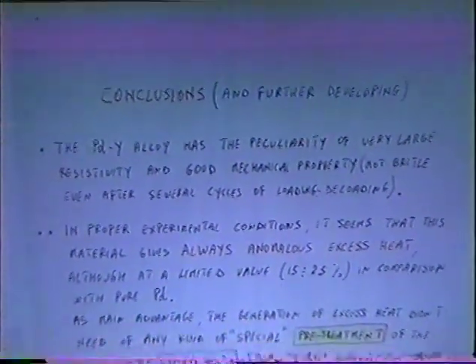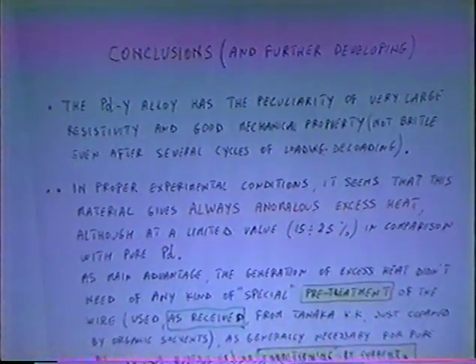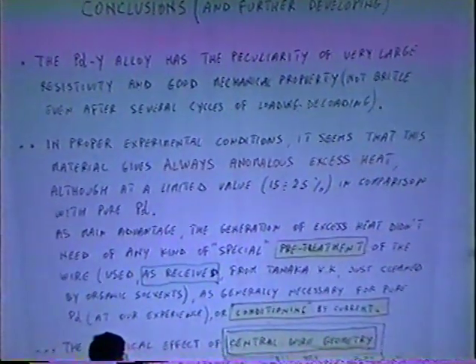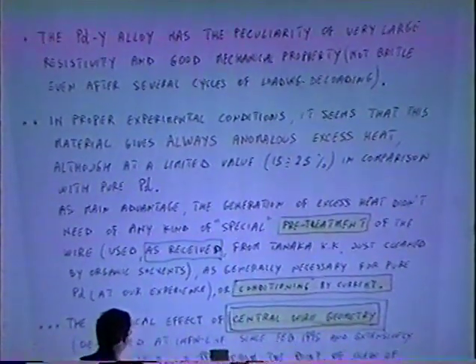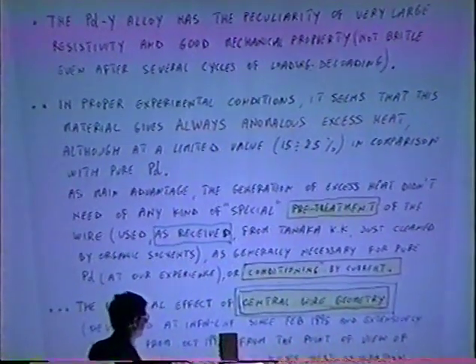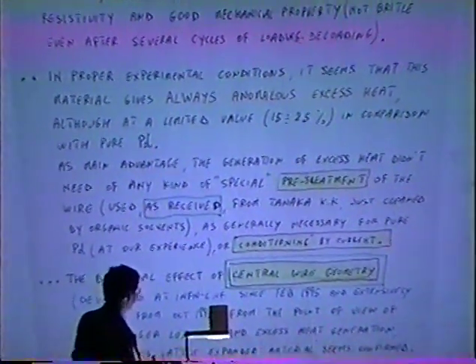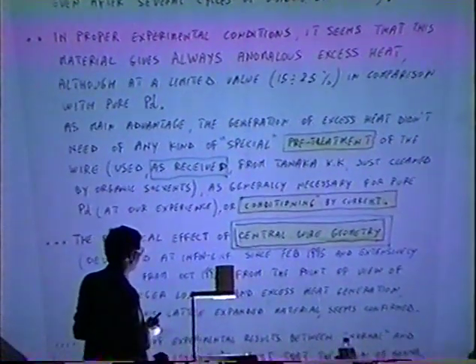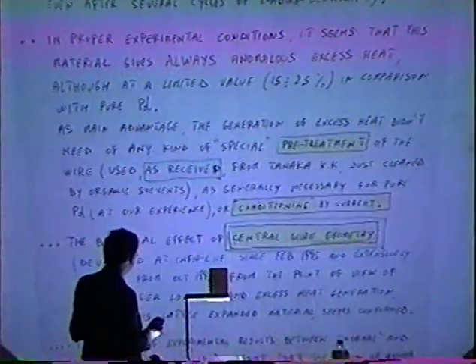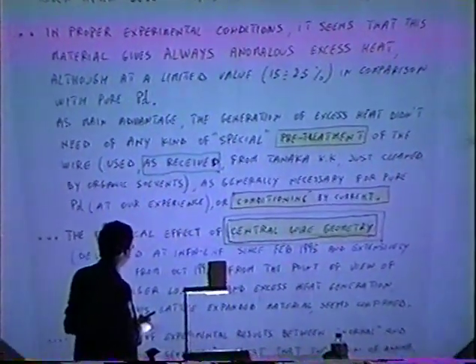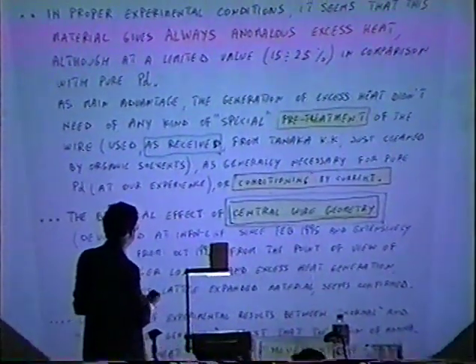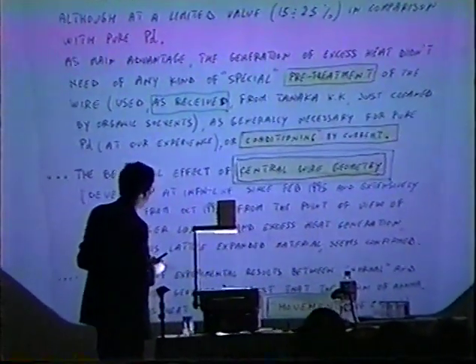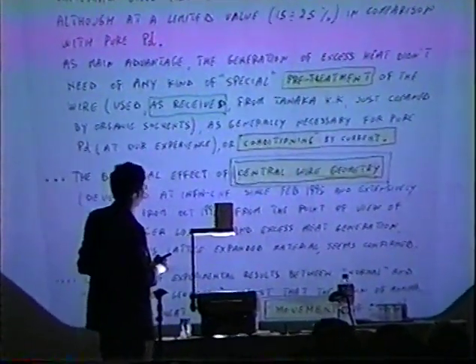Conclusion, or maybe just a starting point for future development. The Pd-Y alloy has the peculiarity of a very large resistivity and good mechanical properties. It's not brittle and stable even after 20 cycles of loading and deloading. In proper conditions, these materials always give excess heat, always, even at a low value of 15-25% in comparison with pure palladium. The advantage is that they don't need special pre-treatment. We use it as received from Tanaka, just cleaned with solvents, and without conditioning by proper current steps.